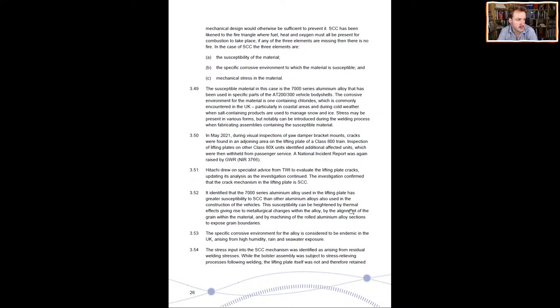So what happened there? The susceptibility is heightened by the thermal effects of the weld, by the alignment of the grain within the material, so the crystalline nature of that alloy, and the fact that they've then machined the rolled aluminium alloy sections to expose the boundaries of the grains. It gets into deep metallurgy, but if you've exposed those, then they can potentially pull apart, unzip and create a crack.